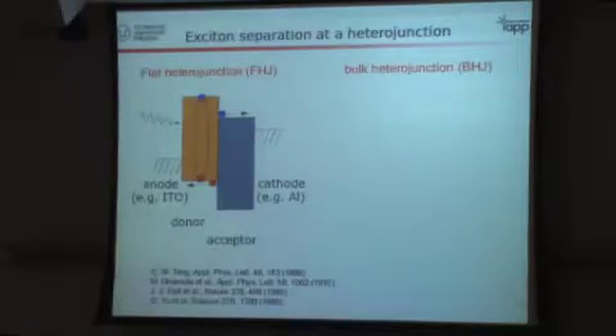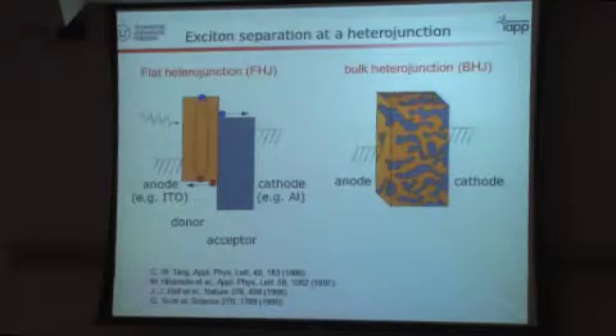Now the way to proceed is known since many years. The first discovery was from Ching Tang, who had the idea to use a heterojunction to separate electrons and holes. So the excitons diffuse to this heterojunction and get separated. Now because the excitons do not like to diffuse, you can also bring the junction to the exciton. And this is done in the bulk heterojunction, which was actually, many people overlook that, invented by Hiramoto in Japan already in 1991. And this way, using this morphology, you can get the junction to the exciton.